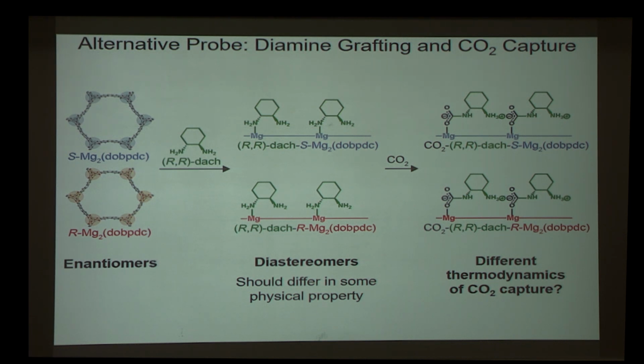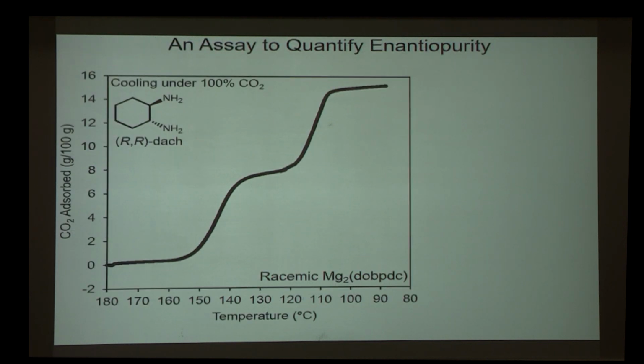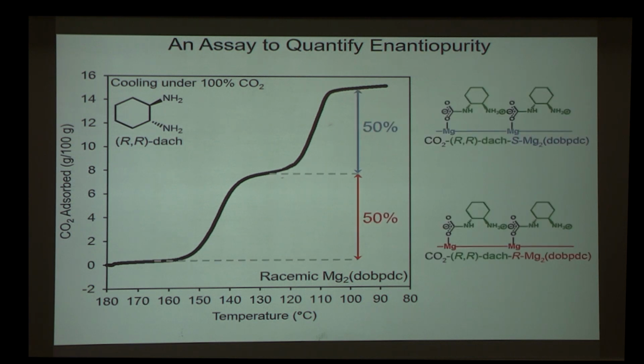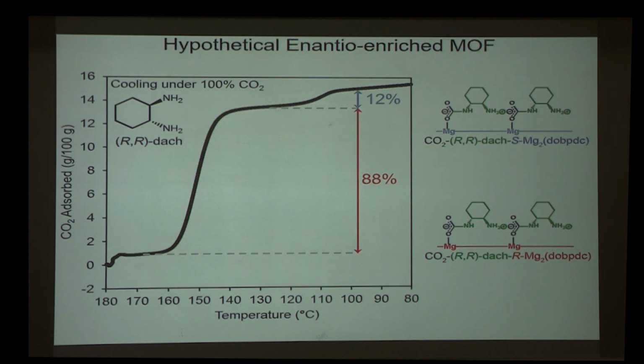So I already told you that when you append diamines to this framework, it can exhibit sharp adsorption steps of CO2 capture. And because these are diastereomers, you can envision that the thermodynamics of CO2 capture may be subtly different. So you may actually see two adsorption steps corresponding to the two diastereomers. And this is how the data look. When the enantiopure diamine is appended to the racemic MOF, indeed, there are two transitions. And I have confirmed that these correspond to the two diastereomers of the material. Now what you could envision, if we succeed in making a MOF that is non-racemic, the data should look like this, where one of the two steps is much taller than the other. And this should be a quantitative approach.